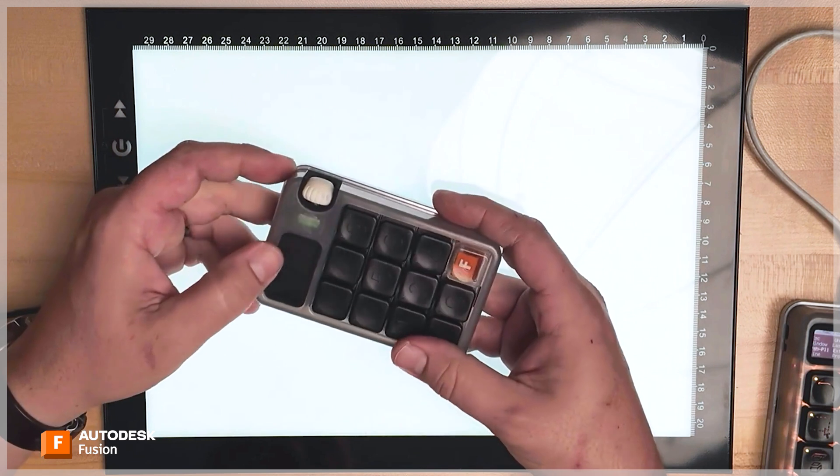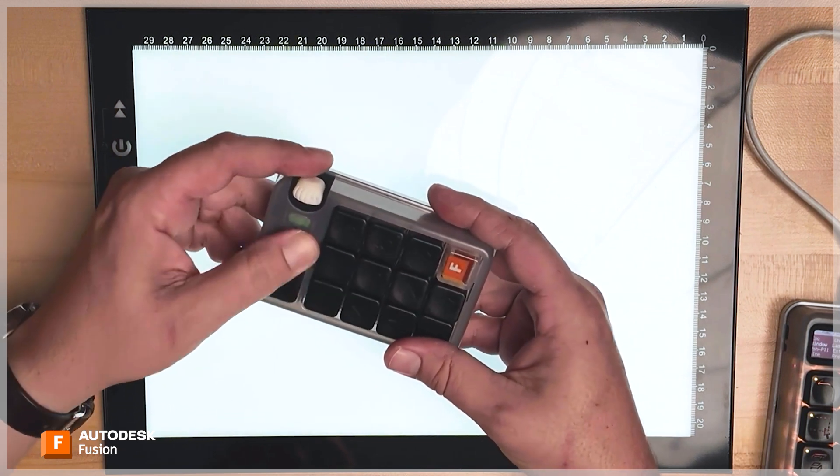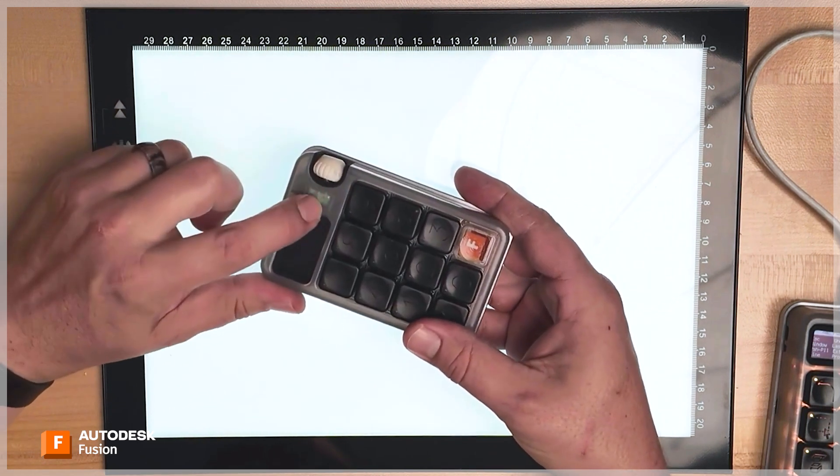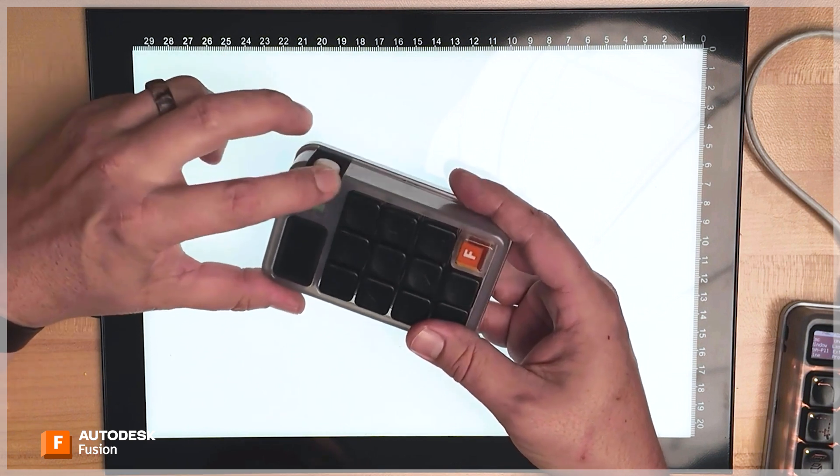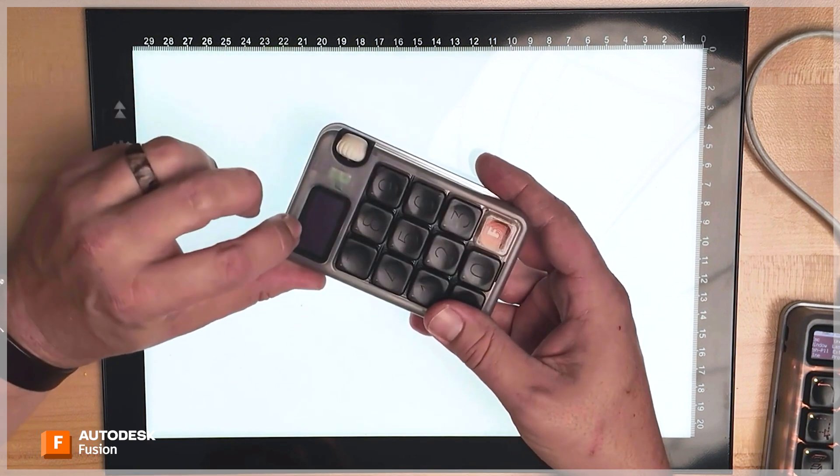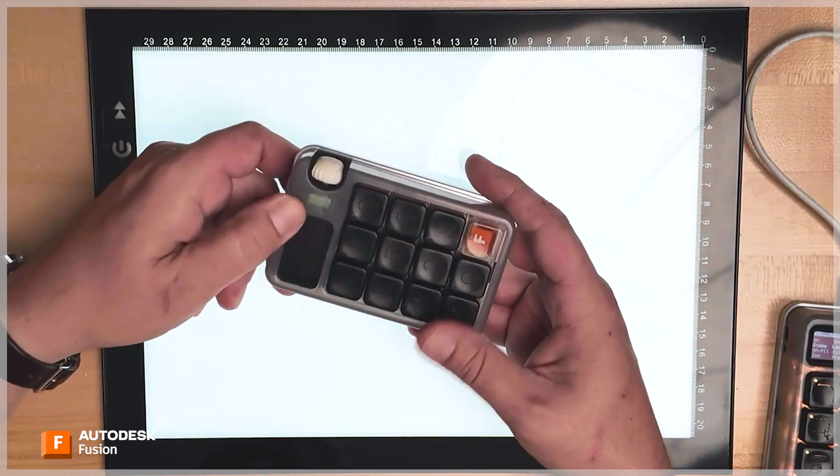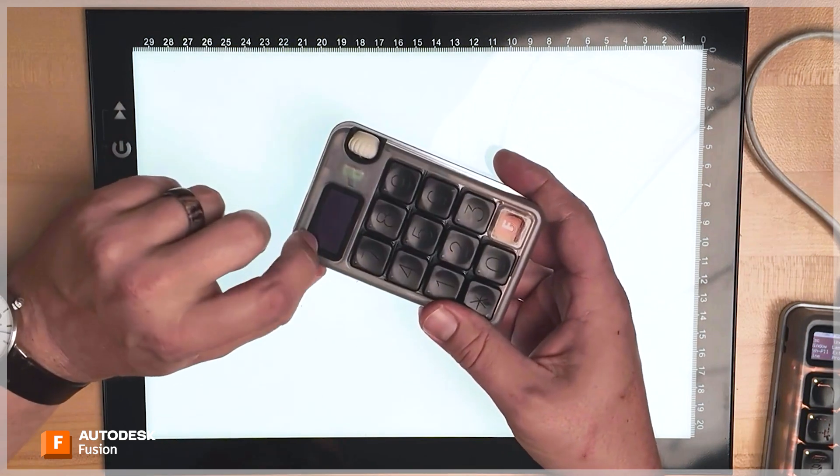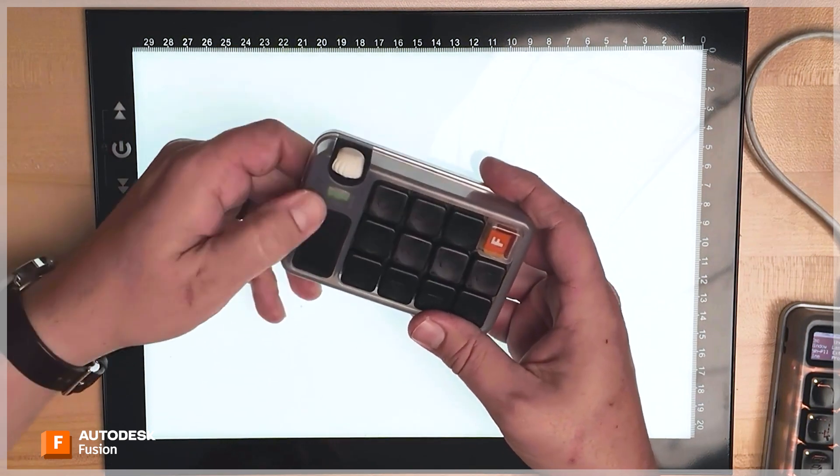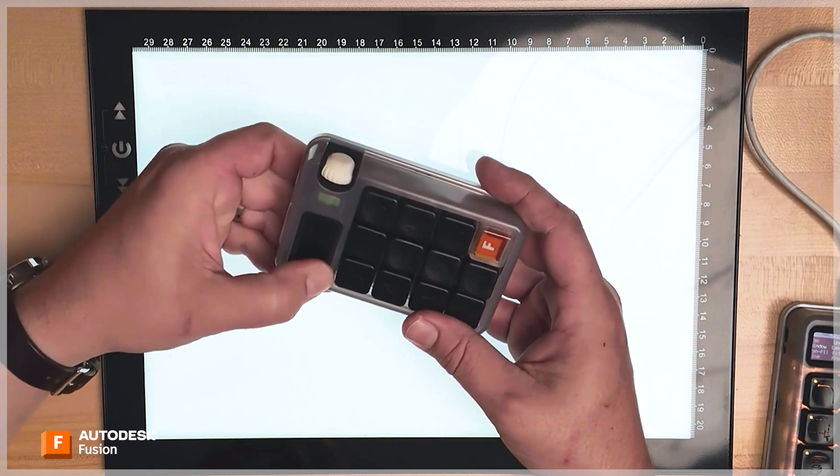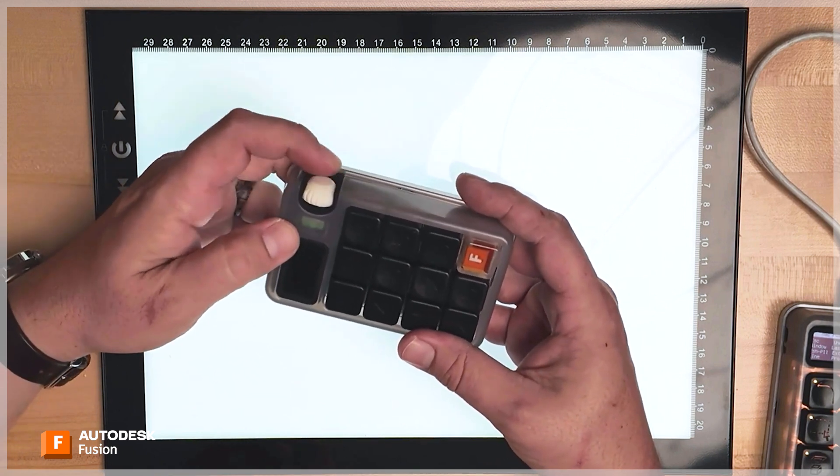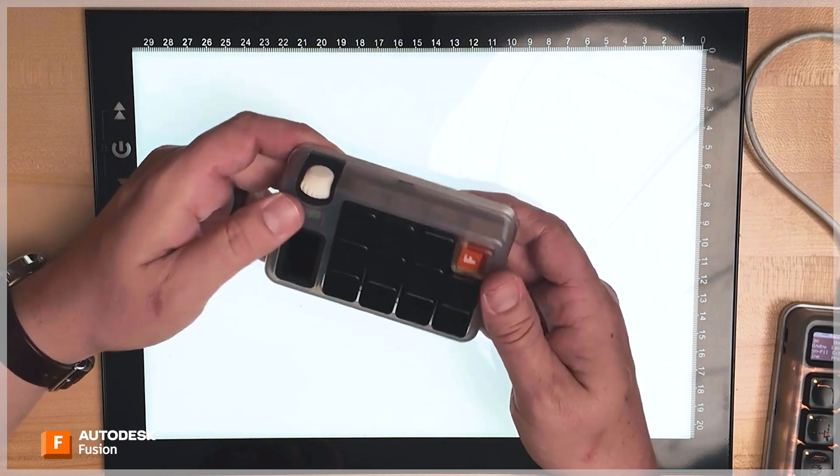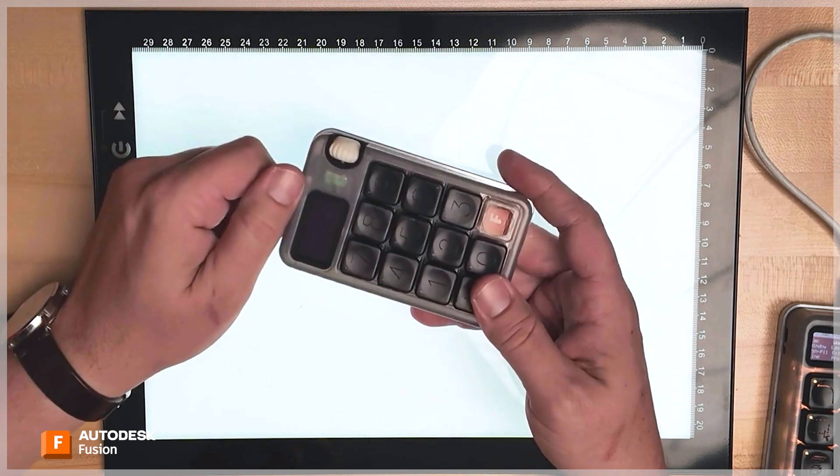Assembling this was tricky. There were some really tight tolerances between these parts. Having this bridge here between the scroll wheel and the bezel made it kind of difficult to put together because the parting line tended to bind on this 3D printed material. The 3D printed material swelled more than we thought it would with the dyeing process. It usually comes off as gray. So that made the interfacing a little bit more difficult here. So with our next injection molded part, we tried to mitigate that with a couple different methods.